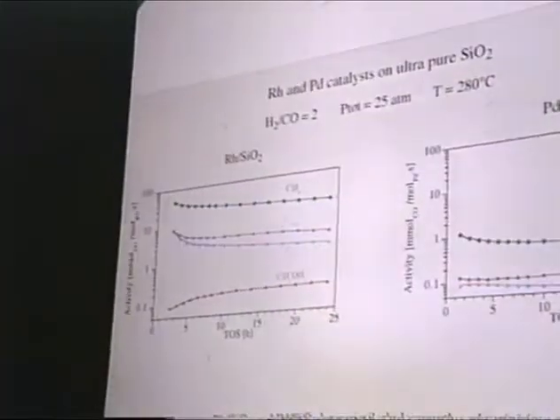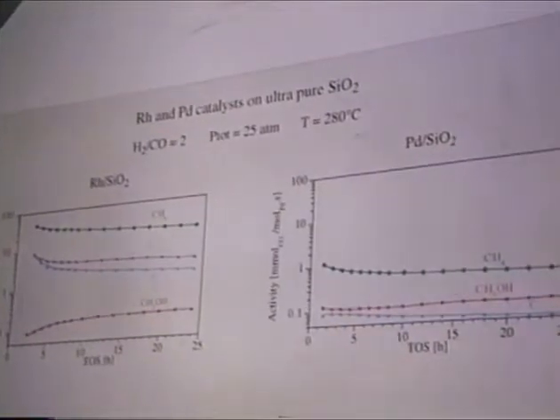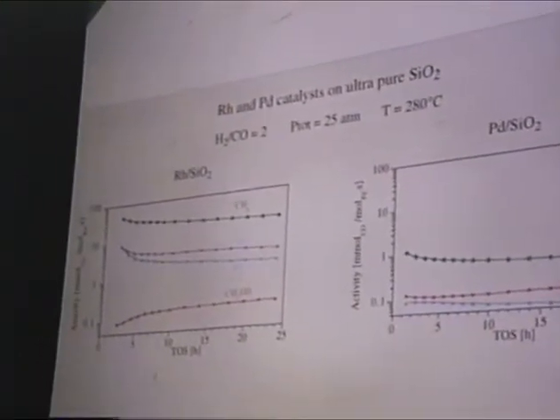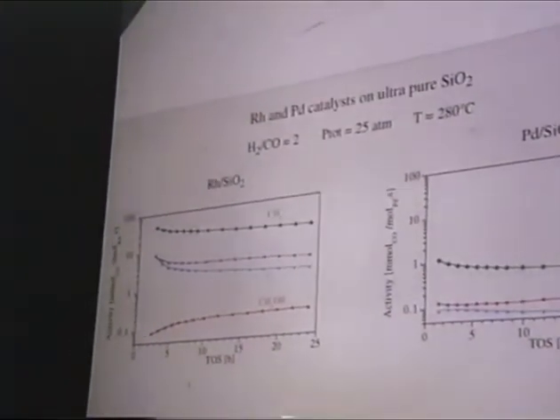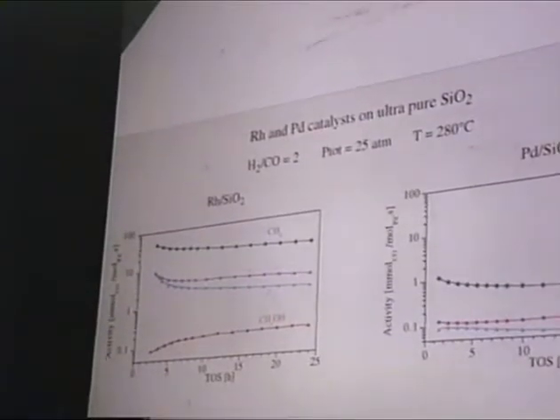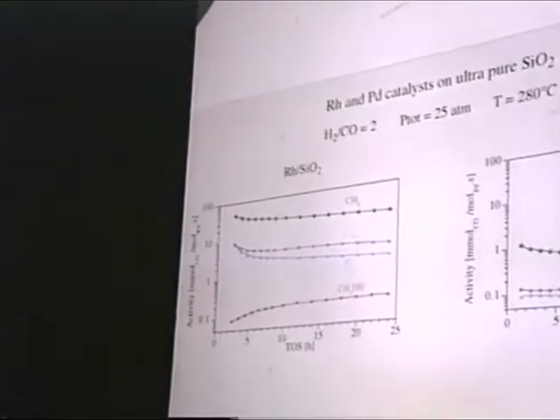So we made our own silica from silane compounds, and we're very careful not to use glass because the sodium and the potassium in the glass can be leached out. So we either used quartz or plastic, and the students had their gloves on, and so on and so on. And when you really do that, you come to the following result.